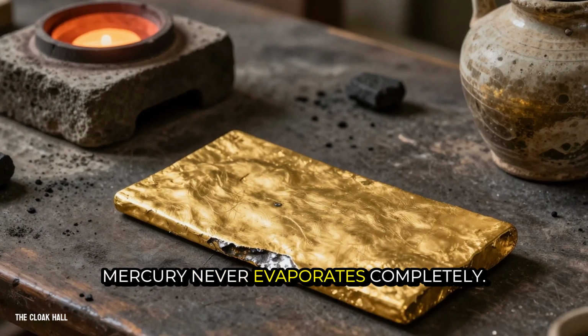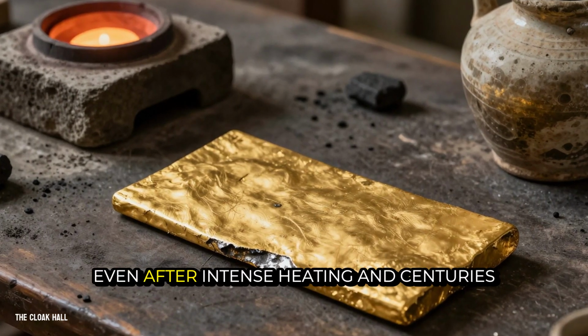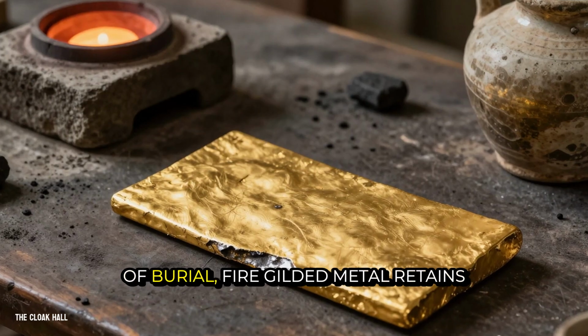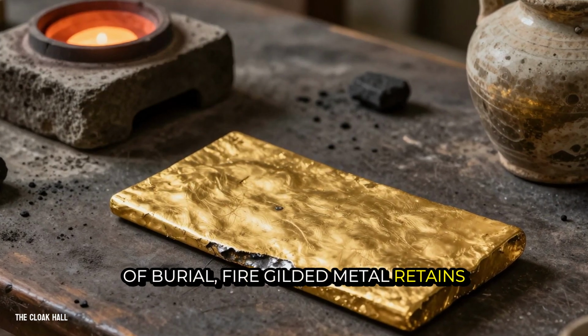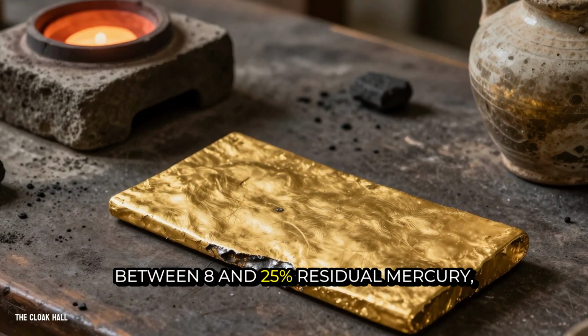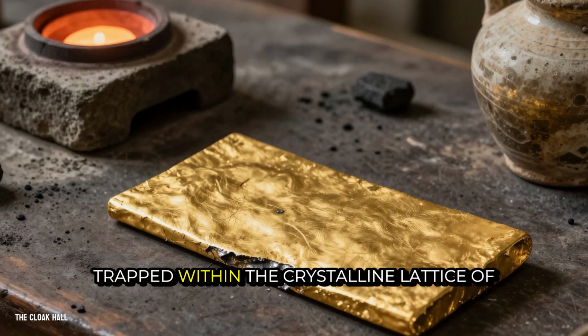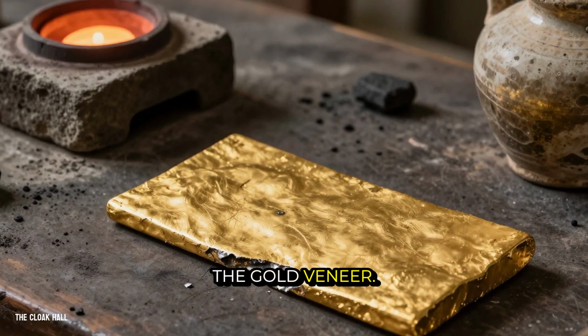Mercury never evaporates completely. Even after intense heating and centuries of burial, fire-gilded metal retains between 8 and 25% residual mercury trapped within the crystalline lattice of the gold veneer.